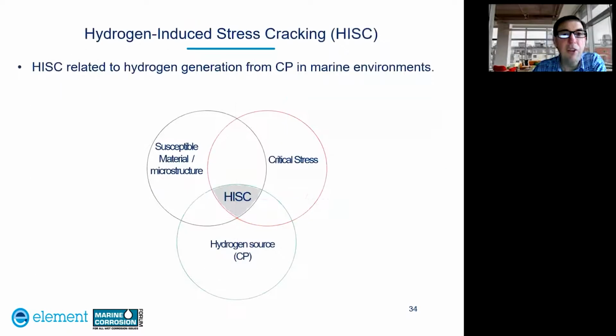So I'm going to skip this slide because of time and move on to discuss hydrogen-induced stress cracking. So HISC is related to hydrogen generation from the cathodic protection system in marine environments. So many of you will be familiar with this Venn diagram that's used to look at stress corrosion cracking. So for HISC, we need to consider the material and whether we have a susceptible material and microstructure. We also need to look at the stress and whether the stress is in a critical region. And finally, we need to look at the source of hydrogen from the CP system.